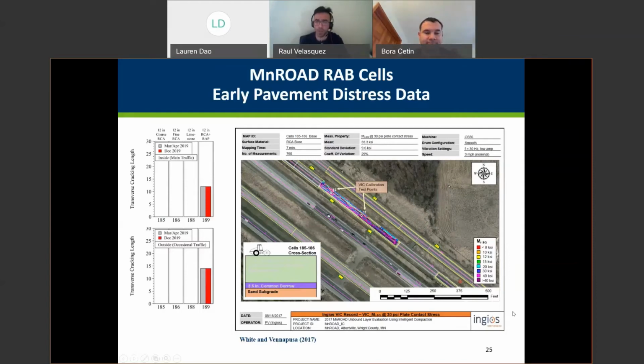Looking back at the intelligent compaction quality data collected from David White and Ingios during construction on both the subgrade and the base material, we observed that the cells that have more uniformity and less spatial variability were the ones that currently don't show transverse cracking. Here I'm showing you the mapping of a resilient modulus for cells 185 and 186. And you see that most of the colors are dark brown and dark blue. You don't see a lot of significant variation.